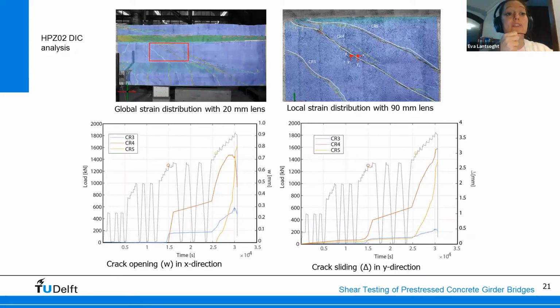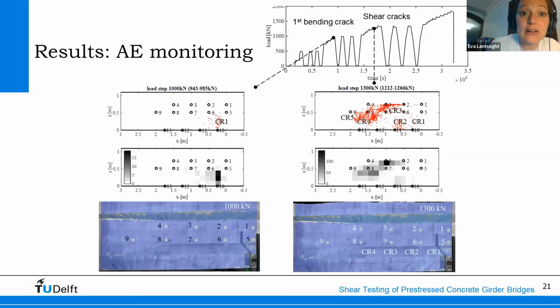Here are some further results of the digital image correlation. So we developed this, or I should say Gabriela developed this over the course of the experiments, but essentially we've been able to calculate the crack opening and sliding. And of course, crack opening and sliding are important input parameters to actually be able to calculate the aggregate interlock on the crack. So with that, we can estimate which part of the shear is carried by aggregate interlock.